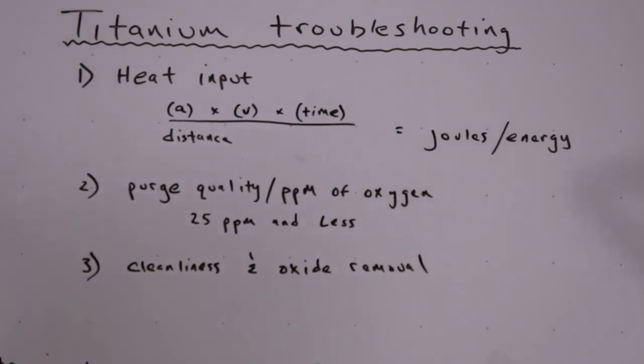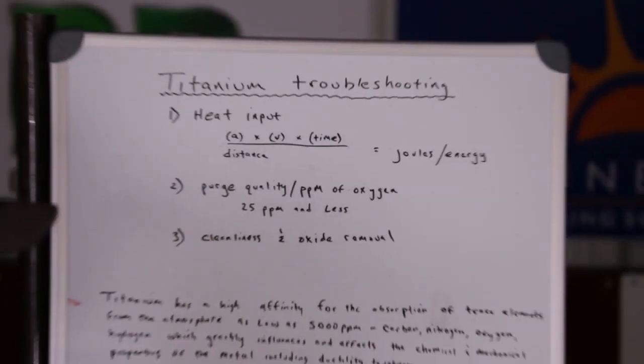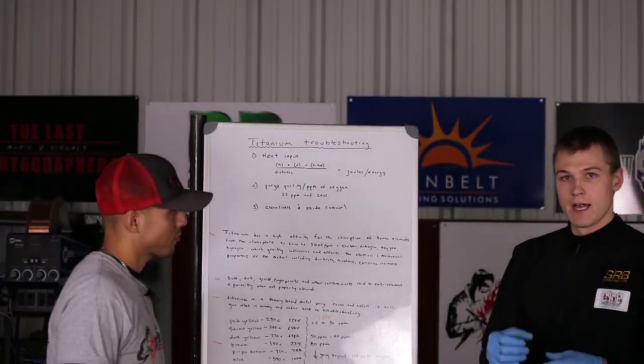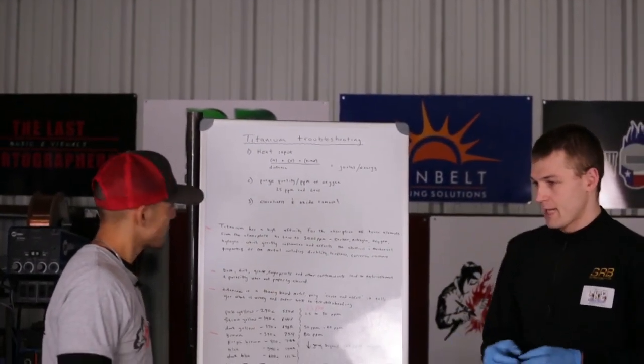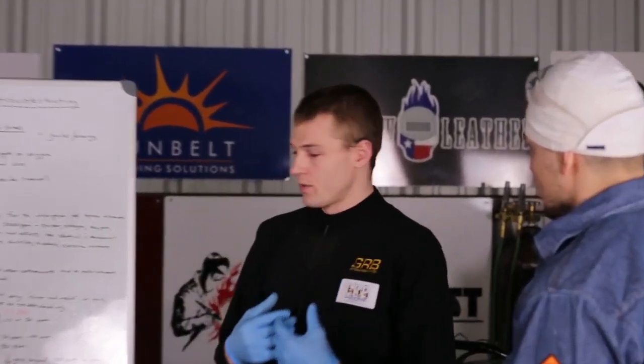And if a person wants to be very specific, they can also change their welding technique where they can expel certain amounts of energy to get over a distance. Say, for example, on titanium, the fill pass, I was shown a technique where you can have the foot pedal down, you can have the filler metal as a lay wire, and you can give a surge of current. It washes the weld puddle out, and then you can drop the current, keep the higher frequency on. But you keep the higher frequency on so that it does not leave any pinholes, it doesn't shut the arc off. But then you move to a leading edge, you give another surge of current. Overall, you can travel a fair distance, and that technique will limit the amount of heat input you expel into the material, and you can get a lot of metal deposition into the material over a distance.